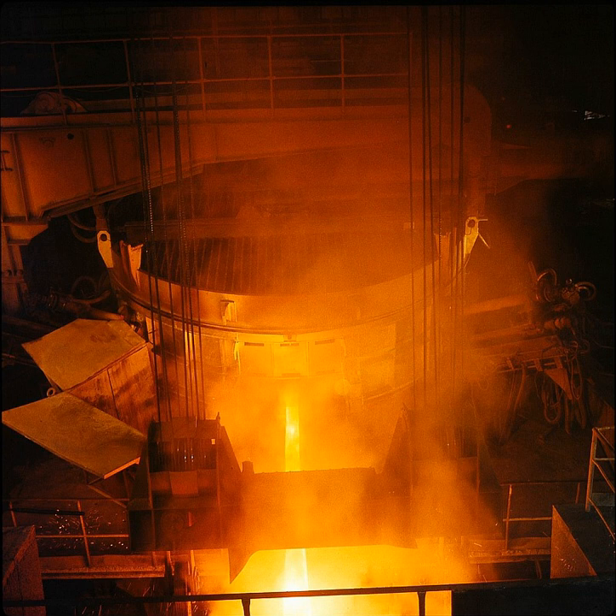A mid-sized modern steelmaking furnace would have a transformer rated about 60 million volt amperes, 60 MVA, with a secondary voltage between 400 and 900 volts and a secondary current in excess of 44,000 amperes. In a modern shop, such a furnace would be expected to produce a quantity of 80 metric tons of liquid steel in approximately 50 minutes from charging with cold scrap to tapping the furnace. In comparison, basic oxygen furnaces can have a capacity of 150 to 300 tons per batch, or heat, and can produce a heat in 30 to 40 minutes.